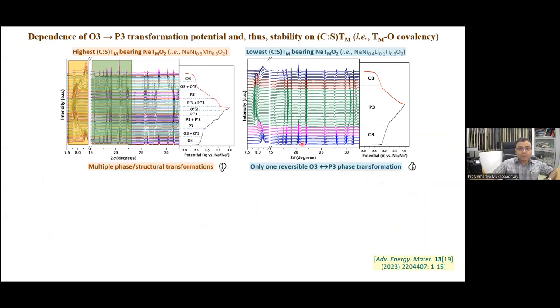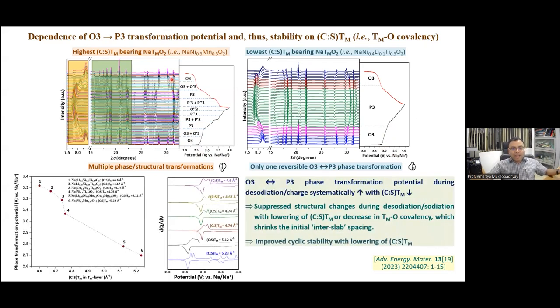When we did the in-situ synchrotron XRD studies, we saw that the highest charge to size bearing material, the unstable one, undergoes multiple phase transformations, basically all possible phase transformations during the charge-discharge cycle. No wonder the cyclic stability is very poor. Whereas the lowest charge to size ratio bearing material undergoes just one reversible structural transformation between O3 and P3 within the same voltage window of 2 to 4 volt. So it explains why this had very good structural and electrochemical cyclic stability and why the other did not. Now, why is it so?